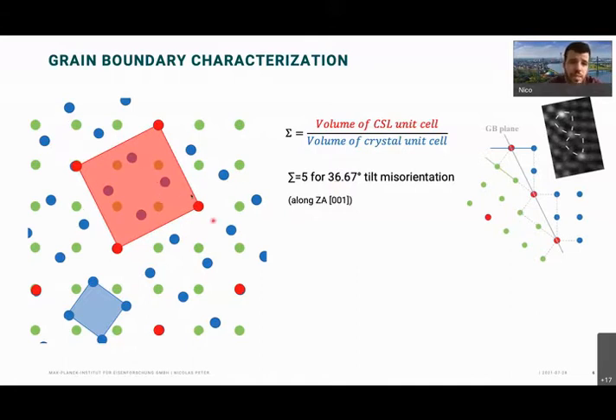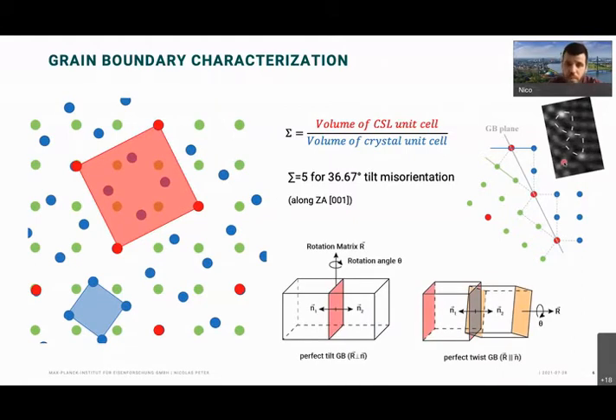And what happens then is you form this dichromatic pattern. If you now take the grain boundary line along these red dots here, and then of course take away the blue dots on one side and the green dots on the other side, you form a grain boundary as shown here. And this is what we're looking at. There's also an experimental picture showing that this actually occurs in nature. So this is what we're dealing with today, mostly.